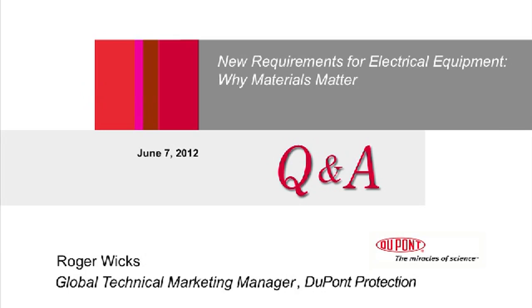Thank you. And then here's a question that asks about the comparison between Kapton and Nomex, and it appears they're looking for differences in the mechanical strength and maybe electrical properties. Yeah, that's a good question too, Gary. Films inherently have very high dielectric strength. The Kapton polyimide film probably is in the range at 1 mil of 6 to 7,000 volts per mil. Nomex paper, the highest dielectric strength Nomex paper type 410, is in the range of 800 to 900 volts per mil. So the films are very high density. They tend to have good initial dielectric strength, whereas Nomex still has very good dielectric strength, much higher than, for example, a similar thickness of Kraft paper.